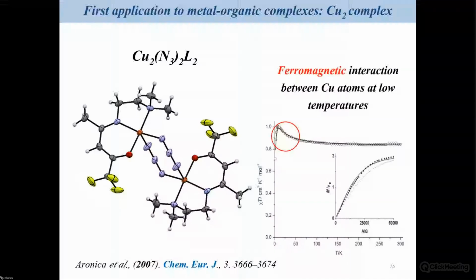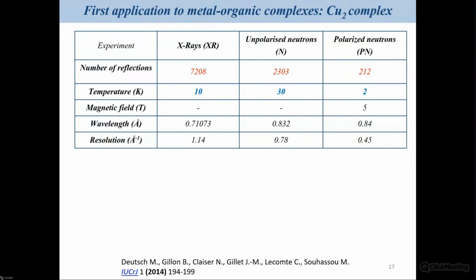And what is interesting in that system is you observe from the magnetic behavior the apparition of ferromagnetic interaction at very low temperature. So the idea of people was to try to understand what is the mechanism leading to the ferromagnetic interaction between the two copper atoms. They made different kinds of experiments: X-ray diffraction, neutron diffraction, and polarized neutron diffraction.